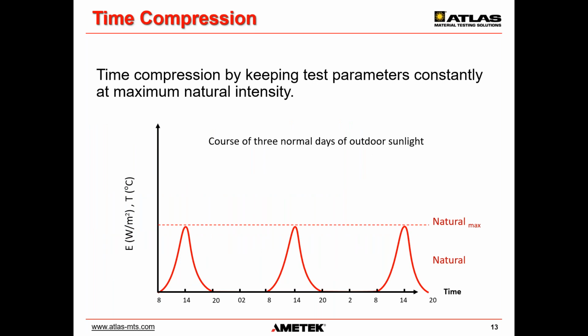How do we achieve it? For most traditional laboratory weathering test methods with artificial light sources, such as the common ASTM, ISO, or SAE methods, the irradiance level is either at or even below the maximum solar intensity you would see during peak outdoor exposures, such as summer noontime. But of course, in the laboratory, we can run at these conditions continuously and just delete the dark night times. You see that?